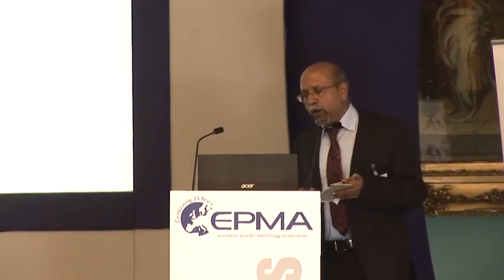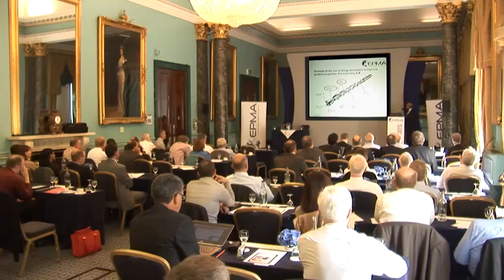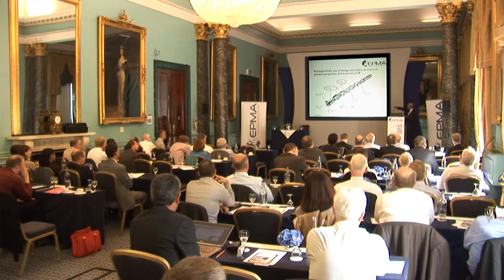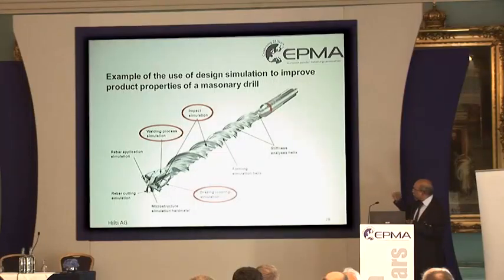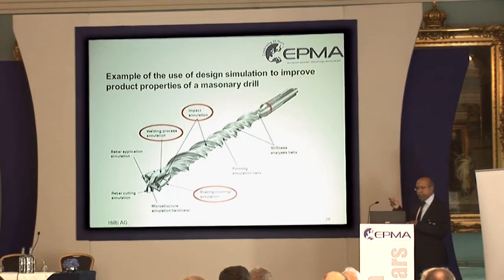We use modeling not only for producing the parts, but also for the end product. This is an example from Hilti, thanks to Steve, where they use the whole process starting from microstructure simulation for the hard metal to manufacturing, that is brazing and cooling simulation, the welding process simulation where the hard metal is welded to the steel shank, and the simulation during application, which means what happens when you have an impact, what happens when you hit a steel rebar when you're working, the design of the helix so that the material which is being drilled can be taken out, etc. So this is just a very simple example.